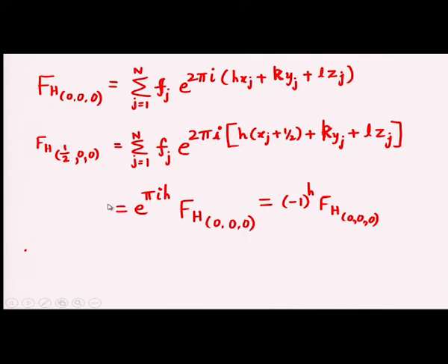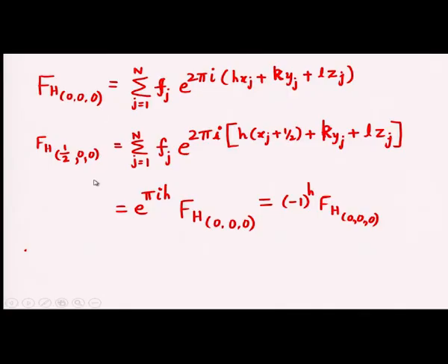Now, from what parities do you have to choose the reflection so that the origin will not change from one to another? Because we have seen that when it changes, a phase factor comes in. So, without change of anything, can you fix the origin at one place, let us say 0 0 0, by choosing a proper set of reflections? Yes, it is possible. By choosing specific parity of reflections, let us say 4 reflections, and assigning particular signs, I can keep the origin fixed at this point 0 0 0. This is known as origin fixing.